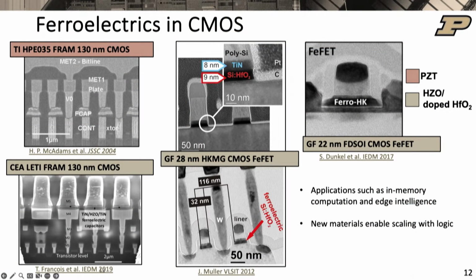So that's not a new concept. Texas Instruments, back in the early 2000s, had this in back end of line. So they made ferroelectric capacitors back in the metal layers using PZT, lead. Okay, that's not something you would normally see in your CMOS, but it's in the back end. It's low temperature processing, so it's not so bad. It's after all the transistor bit is done. And so there are no high temperature steps at that point to infuse the lead and other yucky things into your transistors and ruin them.